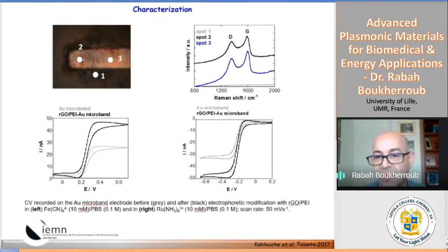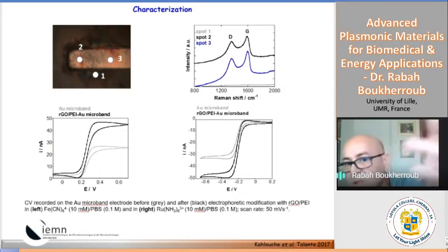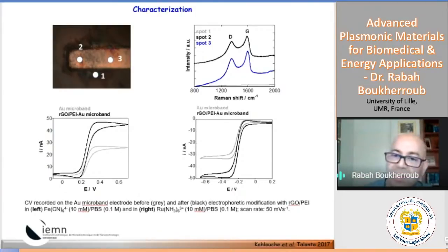Now we just record Raman spectra after graphene transfer. This is the gold, which is about 10 micron in size. Here in spot 1, you see it's a flat line. It means the graphene is not transferred outside the gold. However, if we take it on the gold surface, you see that in spots 2 and 3 you see the characteristic bands of G and the D band. It means I can really functionalize a very small microelectrode in a microsystem.